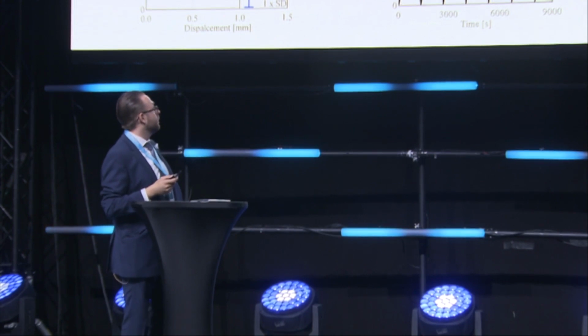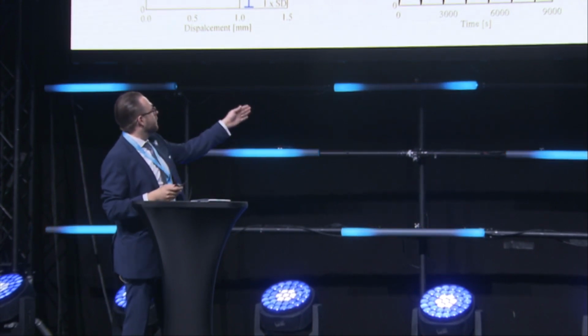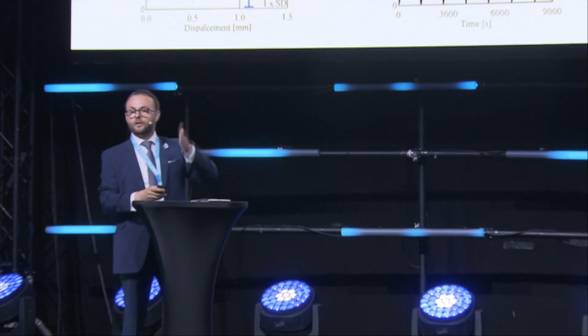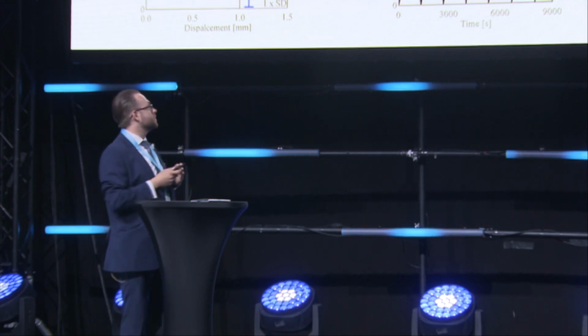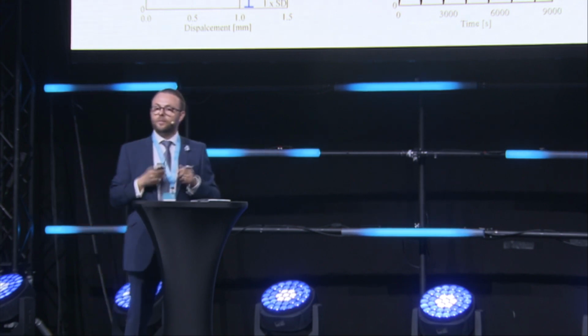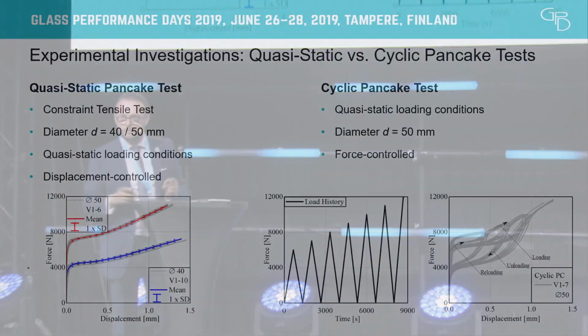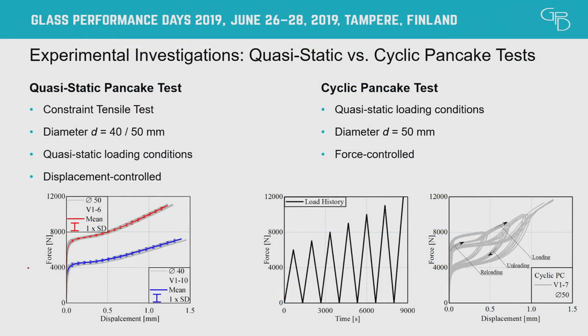So, in summary, what kind of effects do we see? At the virgin loading path, we have a high initial stiffness. Then the softening starts, so the cavitation is growing. The bubbles are growing. If we unload it, we have the typical Mullins effect, a stiffness reduction. And if we have a reloading, then we have a healing effect. So this is really crazy, and we try to put this into one model.